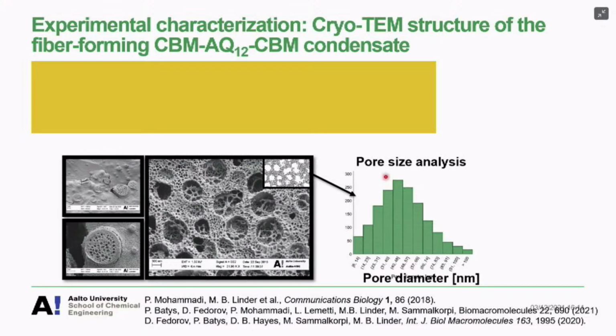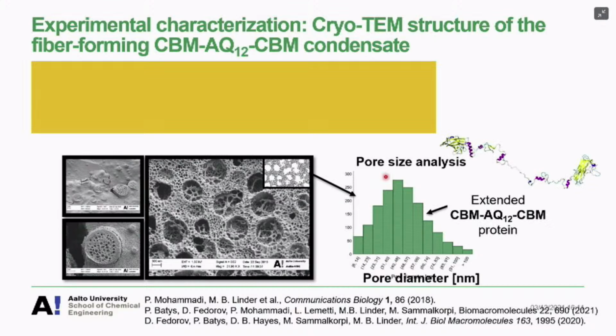And looking at that pore size distribution and considering the protein that is being used to create this condensate, it's quite curious that the extended protein is a little bit over halfway of the characteristic size of those pores. So that actually means that these pores are occurring at the single molecule level. When we realized that experimentally, it seemed a rather good idea to start modeling this. What is really happening there? Why is the condensate structure that way? How are the fibers forming from this kind of material? How do we get biosynthetic silk out of this material from the molecular level?